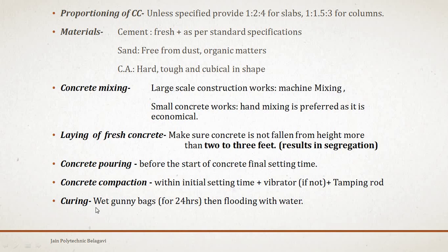Curing of concrete work should be done with gunny bags for at least 24 hours. After 24 hours, water pools can be made with temporary dams on the slabs. These temporary water pools are called flooding with water.